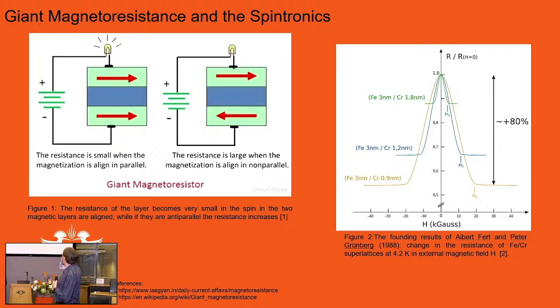Now here's a little light, and you actually want to see. Remember, iron and chrome are metals, so they should be conductive. But in a specific case, I've got spins. Now assume these are little magnets sitting in the iron layer, so left to right. That's known as antiferromagnetic coupling, with, of course, a chrome layer sitting in between here. You effectively have here a switch in control. So what happens is, as the current flows in this antiferromagnetic layer, so chrome sits here with this layer antiferromagnetically coupled, opposite direction and spin, it actually blocks the current from flowing. So you sit here with a high resistivity case.